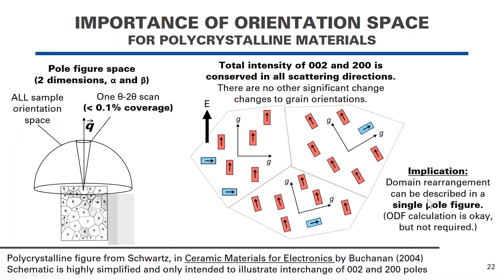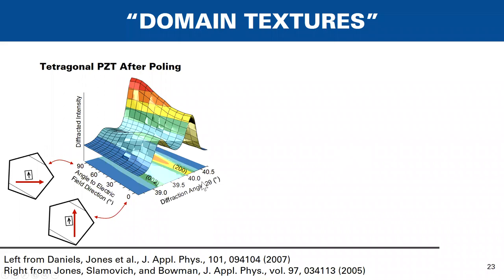Now, the implication of this is that domain rearrangement can be described in a single pole figure. What this means is that we don't have to calculate the orientation distribution function. We can, but we could just sample scattering vectors as a function of space in our pole figure. Okay. So here's some raw data showing that. This, again, is the 002 and the 200 peak of a tetragonal PZT sample, as a function of angle to the electric field, shown over here.